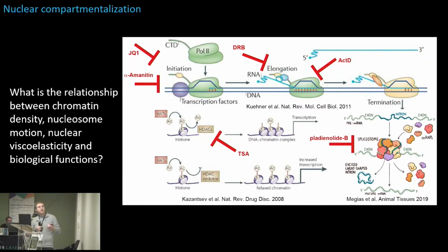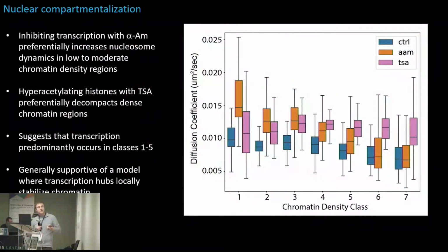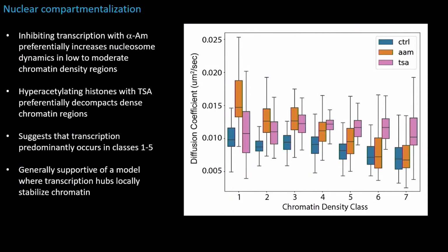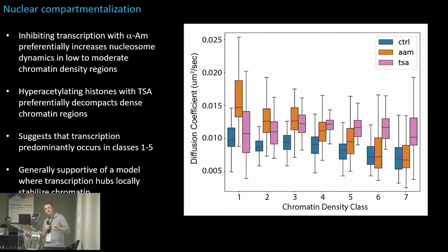I'll just show two examples, alpha-amanitin and TSA, shown here. So if you inhibit transcription with alpha-amanitin, you preferentially increase nucleosome motion in low to intermediate density chromatin regions. Blue is our control curve here, and orange is our alpha-amanitin transcription inhibited curve. So almost no impact on the apparent diffusion coefficient of nucleosomes in these high density classes, but a dramatic increase in nucleosome mobility in these low to intermediate classes. And this would suggest that transcription predominantly occurs in these low to intermediate density classes.